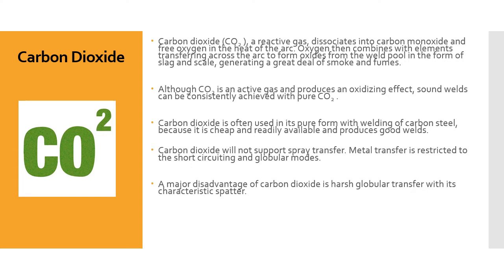Metal transfer with CO2 is restricted to the short-circuiting and globular mode. A major disadvantage of carbon dioxide is harsh globular transfer with its characteristic spatter. On the spatter issue, you really have to dial in your parameters and have someone who knows how to set the machine if you're going to use carbon dioxide, otherwise you're going to have a bunch of spatter. But it's all a learning curve — I've seen guys weld with carbon dioxide that would leave almost no spatter because they knew how to tune in the machine.